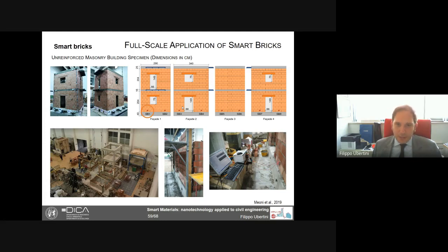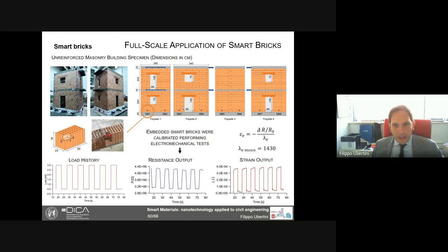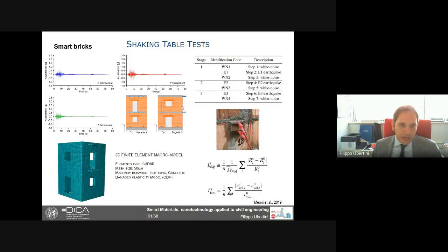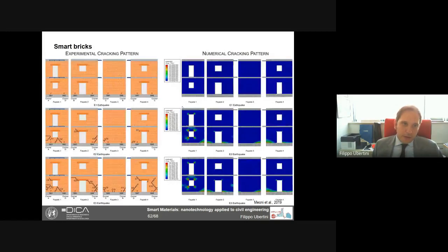testing on a shaking table with some smart bricks at the base. The measurement is the same you have seen. We have done numerical simulation, and we have defined a sort of damage index that considers the absolute relative change in strain at single bricks and in the total bricks with respect to the undamaged situation. Here you see the real damages after different earthquakes from the shaking table. On the right, you see the simulation, which is satisfactorily consistent with the experiments.